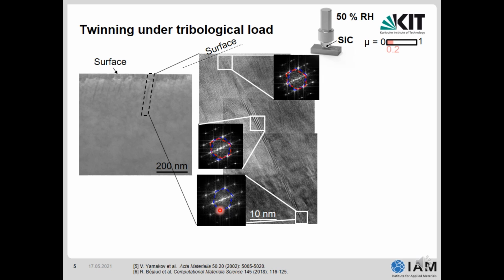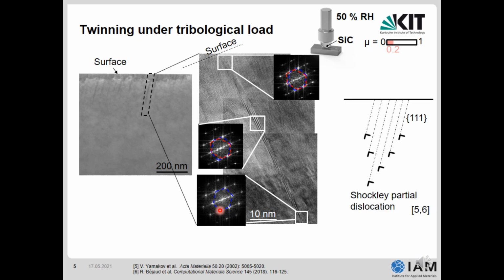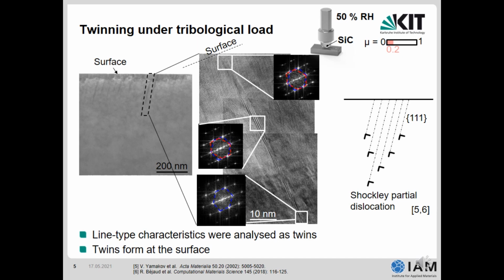So I had a look into literature, which kind of mechanism can form such a twin. There's on one side the Venables mechanism, but for such a mechanism, the distance between the surface and the depth of the twin is too small for such a source to form. So by MD simulation, such a twin formation mechanism was shown. This means that Shockley partial dislocations start here at the surface and then glide into the material, and this is done on several neighboring 111 planes. And this is how the twin forms. So what we learn here is that these line type characteristics are twins, and for me it seems like that the twins form at the surface.